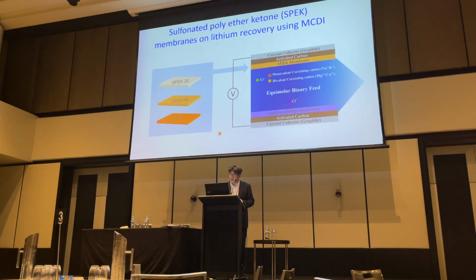the result later on. And we also look at the polymer, because the cation exchange membrane did not really improve the overall selectivity. So we look more specifically at the SPEEK polymer to recover more lithium from this CDI. So we changed the cation exchange membrane, which is SPEEK 20. 20 means 20% of sulfonate group.